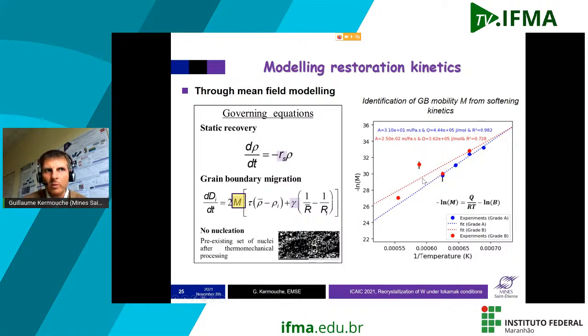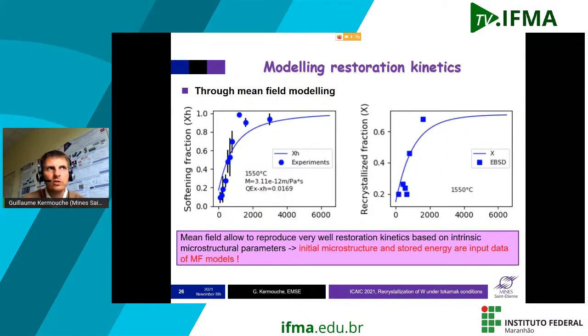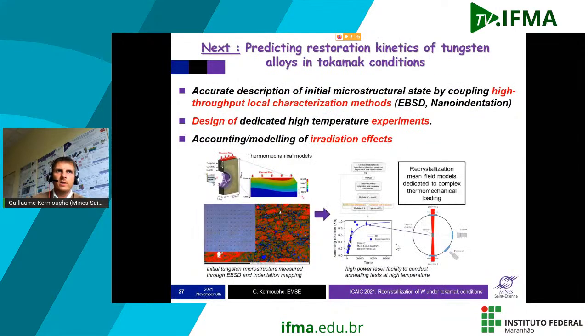So that means that the main difference between the two tungsten is the initial microstructure and not really the intrinsic physical parameters. So from that, we can try to model the recrystallization kinetics, and you can see that it works quite well. We can fit quite well the data from this kind of mean field model. And finally, just by changing the initial microstructure, you will get another kinetics for the recrystallized fraction. So we use this kind of model to take into account the initial microstructure and finally to find the good initial microstructure. So I am at the end of the presentation.